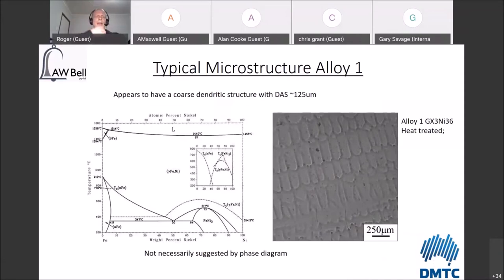Now, one of the things that becomes quite clear about Invar is that it does not have a two-phase solid plus liquid range while you're going through the solidification process. You're going from liquid directly to austenite. So basically, you don't go through liquid goes to solid plus liquid goes to solid, you go liquid goes to solid in the same way that a pure material does.